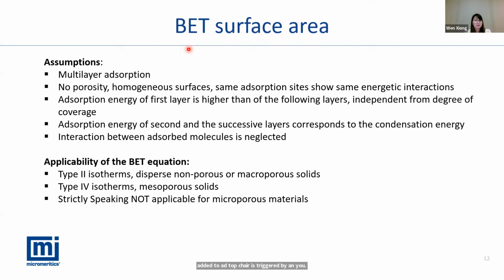But later on, the three BET researchers found that Langmuir's assumption of one molecular layer is not suitable for most cases. So they gave their own assumptions. They talked about five different kinds of adsorption. The biggest difference from the Langmuir model is multilayer adsorption versus monolayer adsorption. They also assume the interaction between the adsorbed molecules can be neglected. What they consider important is the interaction between the adsorbed molecules and the surface. So they found different isotherm types, which, as we already know, have been clearly reported by IUPAC. We have different kinds of isotherms.